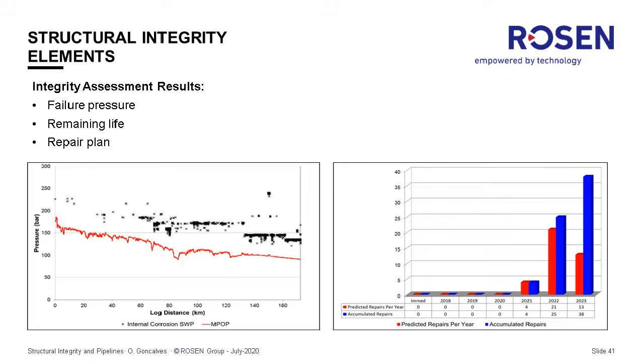These are the features, and the y-axis is the failure pressure, and the red line is the maximum operating pressure of the pipeline. Usually it's not constant. It changes along the pipeline, especially for liquid pipelines. So the meaning here is that all the features in this particular pipeline have a failure pressure above the maximum operation pressure. So that means that there's no immediate danger.